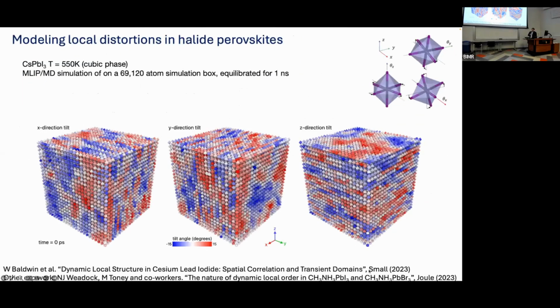In addition to that, it's able to map variations of the structure. And what's surprising to us around that time was that the structure is actually so dynamic. In this case, what I'm showing is a sort of a snapshot of an MD simulation. And what we're cataloging is the octahedral tilting as a way of showing how much structural change is occurring. And there are 3 slices here, depending on the direction of the octahedral tilting, so X versus Y versus Z. And this is the degree that it's tilting.